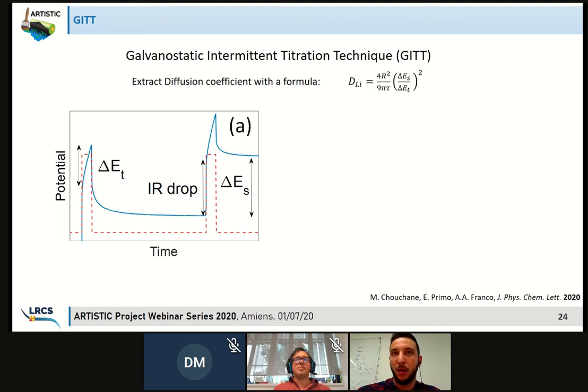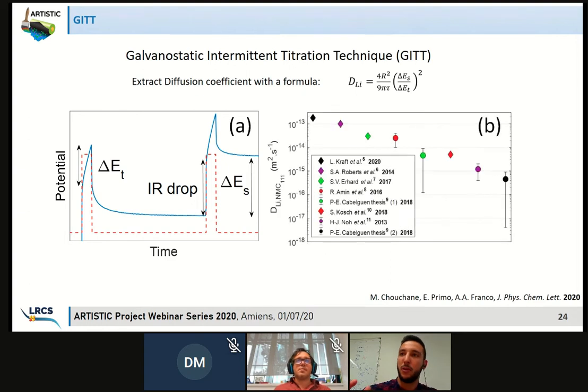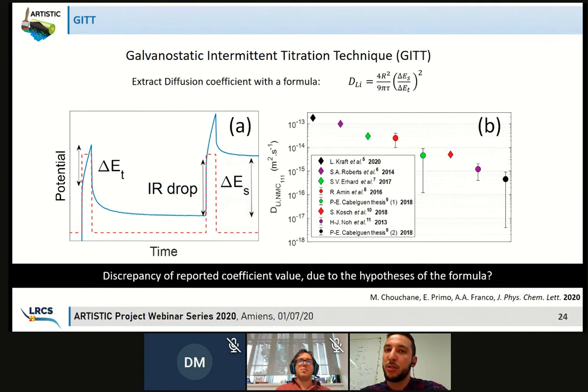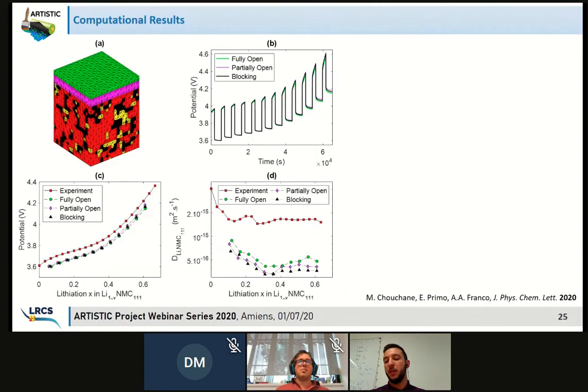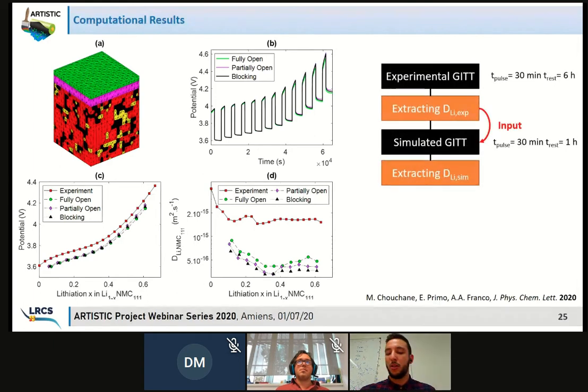However, when we look a bit further into the literature, we have noticed that there was a wide dispersion of reported values for here the NMC 111, and the range of years is not like huge. It's on 6 years. There has been 4 orders of magnitude almost between the highest and the lowest diffusion coefficient reported. So we asked ourselves if the discrepancy in reported values was because of the hypothesis behind this formula. So what we did is we applied this given workflow.